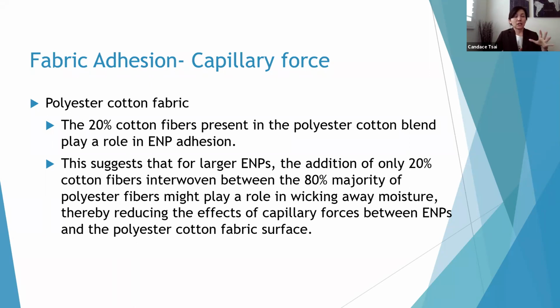This makes the overall interaction of nanoparticle onto the surface of the fabric much lower. It makes cotton and polyester cotton release nanoparticles much more easily because the capillary force has been significantly reduced due to the moisture in the air.